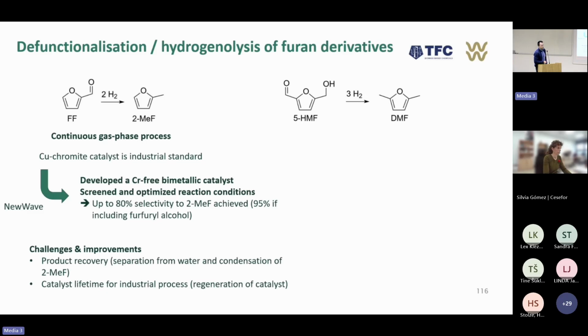Within the NewWave project, we developed a chromium-free but bimetallic catalyst, and screened and optimized the reaction conditions. The best results we achieved were a selectivity up to 80% of methylfuran, not including furfuryl alcohol, because one of the byproducts is furfuryl alcohol. But for us, as a furfuryl alcohol producer, it's not really a byproduct. If we include this product in the selectivity calculation, we basically get a selectivity of 95% to interesting products for us.